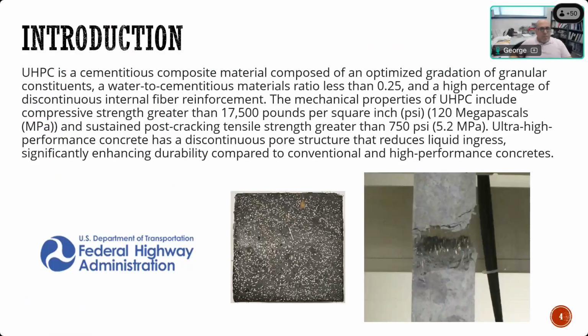And in addition, it also has a high percentage of discontinuous internal fiber reinforcement. As you can see in the picture here, this is a specimen being pulled in tension, and you can see these fibers sticking out of the concrete, bridging the gap between the two parts until failure. And in the cross section, all these little dots are pretty much the fibers. So it's a high percentage of fibers that provide tensile capacity of the concrete even after cracking, and that's the main point. You don't want the concrete to lose its capacity once it cracks; it can also sustain. That's why it's called sustained post-cracking tensile strength, of at least a minimum of 750 psi. Most of the time we get higher than that, 1,000 or 1,200, or even sometimes 1,500.